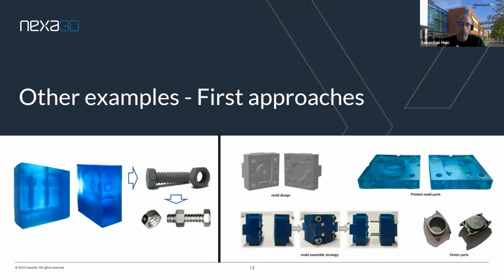So when this material that you remove from the mold swells a little during this demolding, then you have the risk that you see at the bottom right, that you may crack a part, especially when you have some internal material that when it expands will press to the outside of the part. So I hope you can understand that. That's why, for example, in the lower bottom right, you can see this crack on this mold watch case at the top due to this slight swelling.